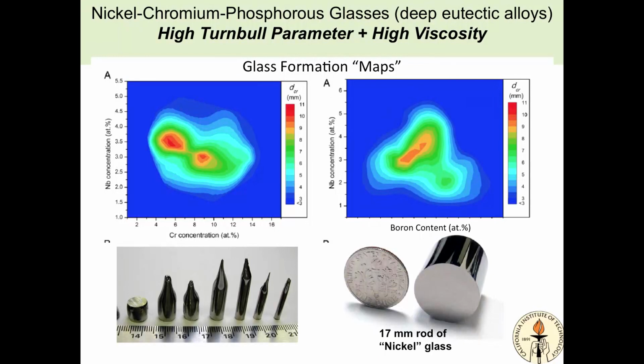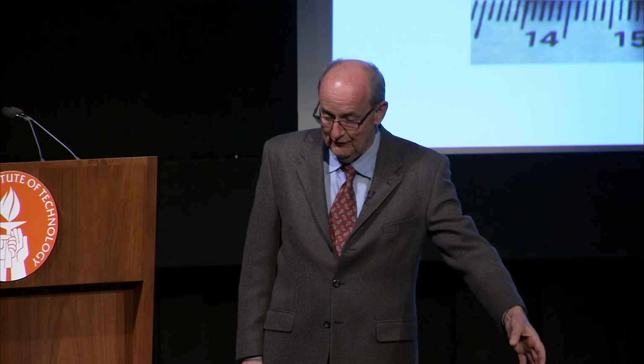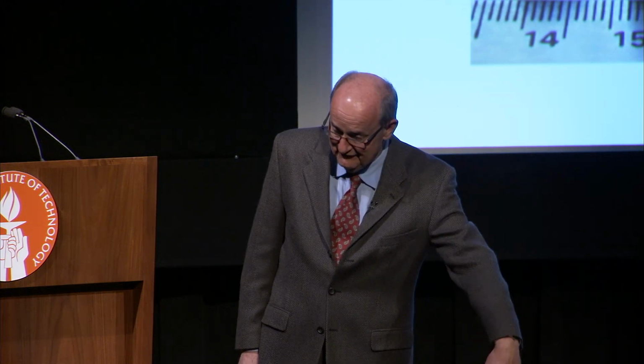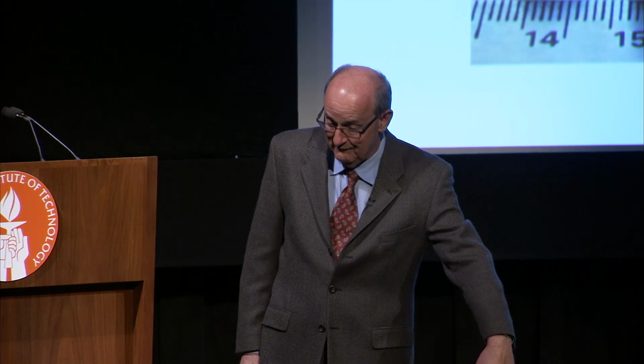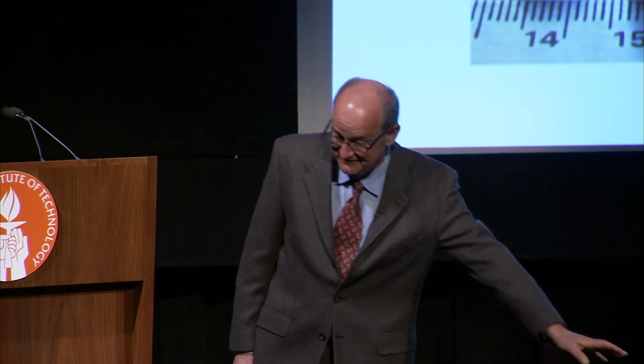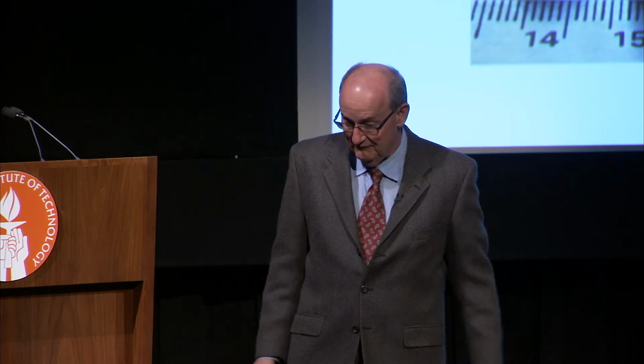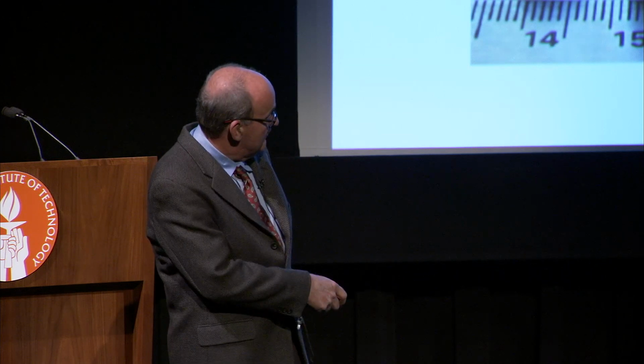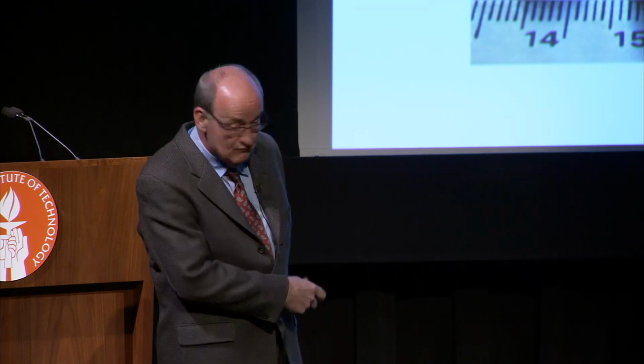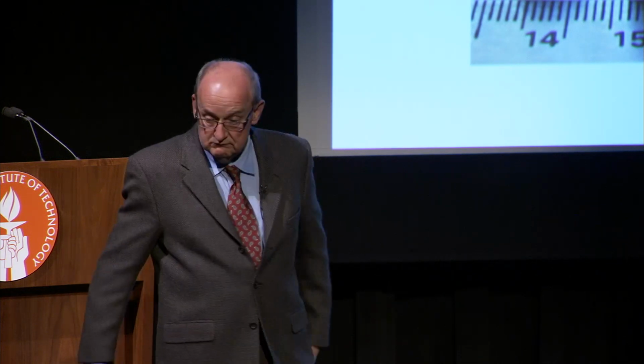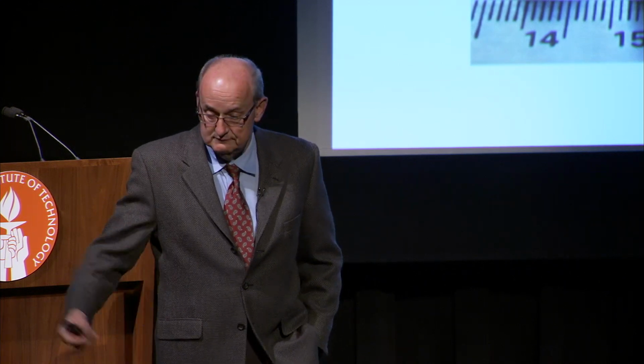It's kind of like stainless steel. That's a 17 millimeter rod of it. And you just heat it up, melt it, cool it in a quartz tube, use silica, because we don't want something that has crystals. That would seed the crystallization. So we melt it in a quartz tube, we quench it in water, and we make amorphous stainless steel.